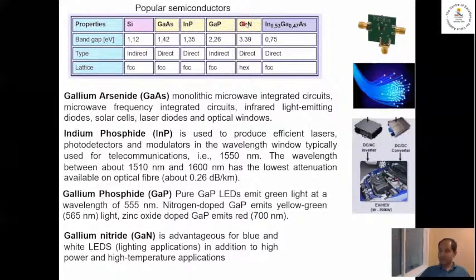And then there's also gallium nitride. This is turning out to be an important material because the band gap is very large here, 3.39 electron volts. So that means you can make optical devices with a shorter wavelength. For example, if you want to make blue LEDs, then gallium nitride is good for that. Gallium nitride is also being used to make white LEDs for lighting applications. It's also an important material for high power electronics.